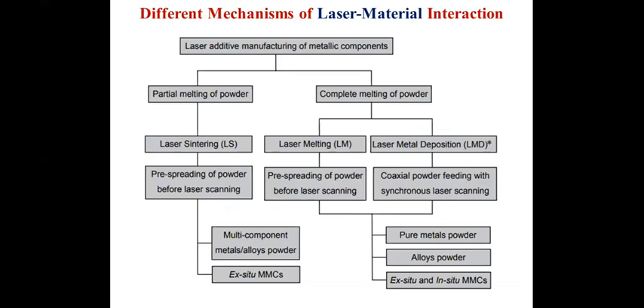There is a mechanism behind the laser additive manufacturing process that comes from the interaction of the laser and the material. The two mechanisms shown here are the partial melting of powder mechanism and the complete melting of powder mechanism. The partial melting mechanism is the reason for laser sintering of multi-component metals and alloy powders. And laser melting and laser metal deposition use the complete melting of powder mechanism, using pure metal powders or alloy powders.